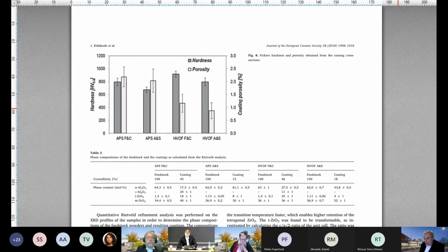Fused and crushed and this agglomerated, or what was it? But if you look at the image, number 8, I would say that they are identical, taking into the deviation of those measurements. Yeah, they do fall within the deviation, but it's a propensity to find conclusions, I guess. Yeah. Based on these deviations and averages, it's likely that this would be the case if you would continue testing more and getting the deviation low. Exactly. But from this, yeah, it's a small stretch. Yeah, but not that much significance.